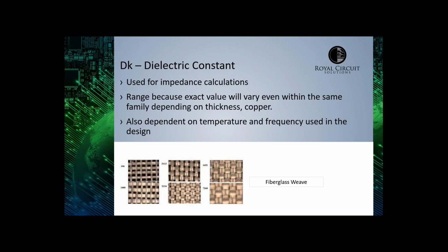This really is in reality a range, because the exact value will vary within it, depending upon copper thickness, the thickness of the laminate, as well as how it's made. So in the bottom below, I have different pictures of fiberglass weave, where 7628 has a much bigger weave, all very tight together, compared to a 106. This has a definite effect on the dielectric constant. For calculations, it's easiest just to use one number, so 4.2 is what I use for FR4. But when you start to really dig into it, you discover that a 5-core FR4 will have a very different dielectric constant than an 18-core. Roughly, it's about plus or minus 0.5 within the family.